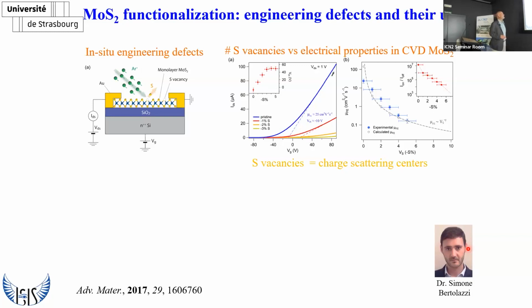What we decided to do: molybdenum disulfide, in the best case scenario, the Scotch tape one, flakes, the monolayer, every 10 by 10 nanometers you have a sulfur vacancy. So the idea was to make use of it, because sulfur vacancies, like defects in any case, are reactive sites. But one defect every 10 by 10 nanometers might not be enough for you. You want to have more reactive sites. So in this study we used the argon beam of the XPS to generate defects, to extract sulfur atoms to create more and more sulfur vacancies.